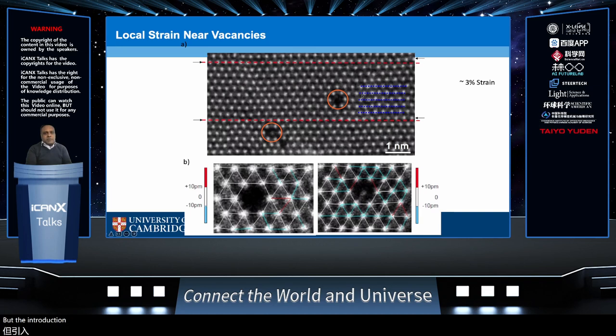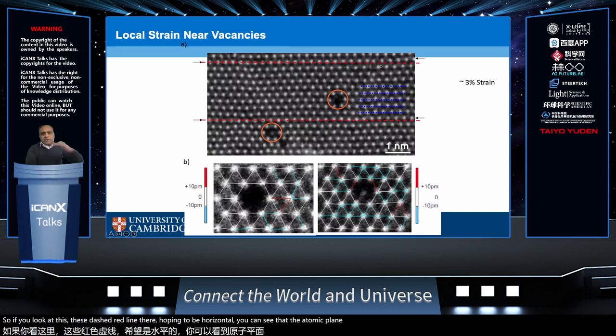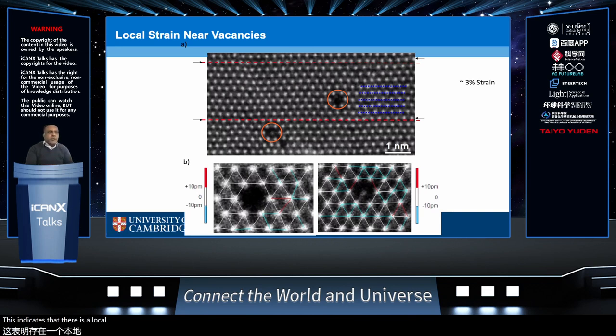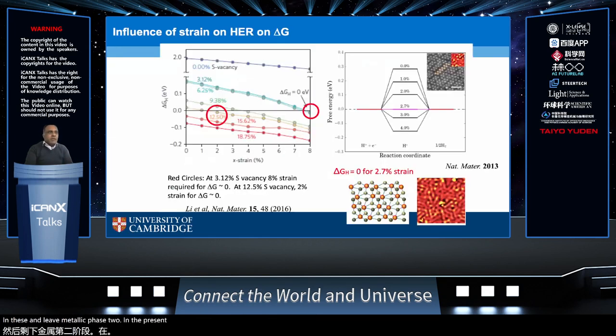But the introduction of sulfur vacancy also introduces local strain. So if you look at these dashed red lines that are perfectly horizontal, you can see that the atomic plane is shifted from the horizontal line. This indicates that there is a local change in the local bonding, which of course introduces strain locally. And strain is a very important factor in determining the thermodynamics. And we've estimated strain by measuring these local distances to be around 2 to 3% in these metallic phase MoS2 in the presence of vacancies.